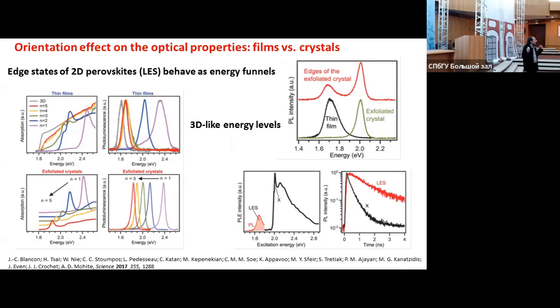When you cast the perovskite on the film, no matter how pure it is in its single crystalline form, and you see this is reproducible, what I showed you before. This is the emission on exfoliated, clean crystals. When you go and cast it and measure the same properties on a film, it's not the same. The most characteristic example happened for this crystal, the n equals 2 example. So you have a single crystal, you have this emission here, and you get a film, you have an emission here for the exact same composition.